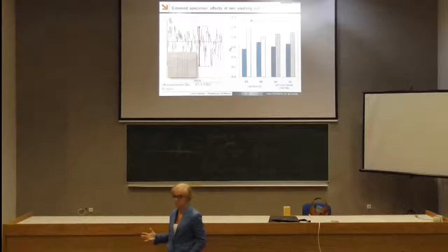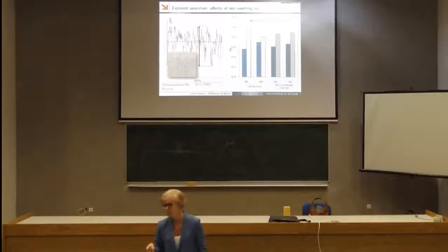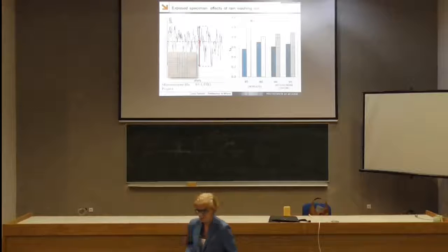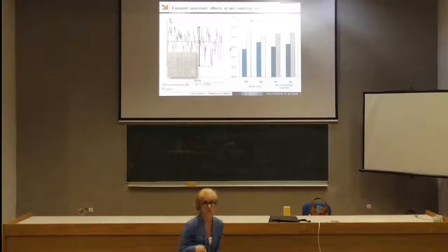And this is true if we have the untreated stone, but it's true the same. A small roughness is developing also on the treated specimen on site. So we can say that, of course, we can treat, we can protect the marble, but at the same time we have to be aware that also the coating is subjected to deterioration by rain wash or rainfall.